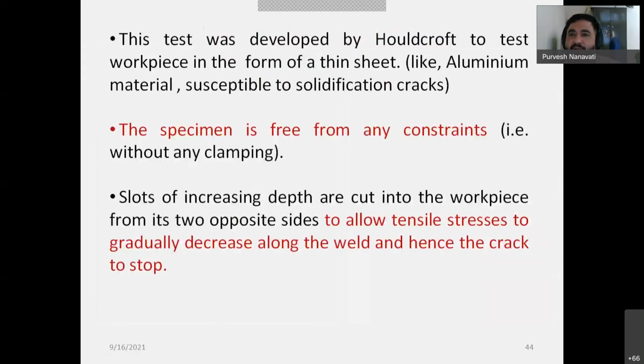Now here we can understand. This test is developed by Houldcroft to test the workpiece in the form of thin sheet, like aluminum material, susceptible to solidification crack. If you are working with a thin sheet and you want to find out the susceptibility to solidification crack, the test is an ideal test. This is a customized test, right?